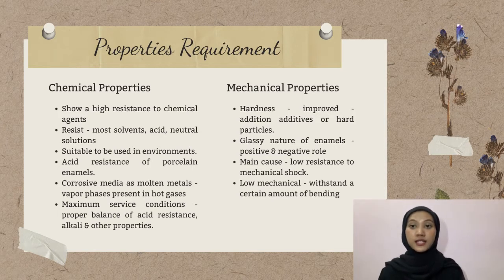For example, the acid resistance of porcelain enamels can vary widely depending on composition and to some extent the processing used. Even such corrosive media as molten metals and vapor phases present in hot gases have been confined within porcelain enamel structures. The degree of attack by acid solution on porcelain enamels appears to depend less on the type of solution than on its pH. The highest degree of acid resistance is obtained by sacrificing other desirable properties such as alkali resistance. To achieve maximum service conditions, a proper balance of acid resistance, alkali resistance, and other properties is necessary.